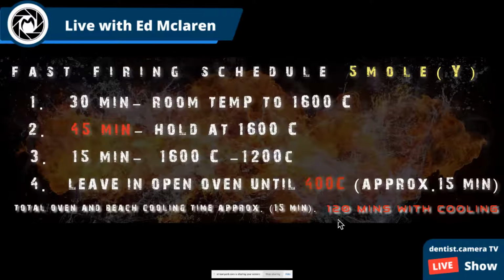You're in and out of the oven from the time you push the start button to the time you can touch it. Okay, so that's what this number is here, the time you can actually touch it. It's about 2 hours. And yes, there are a couple of materials, like that is a benefit of the Noritake material. You could probably cut that down to maybe 80 minutes, okay, 75 minutes, and still have all the physical properties. And we tested everything. We tested this, and all this stuff has been in the IADR, and I know I haven't published a lot of it, my bad.